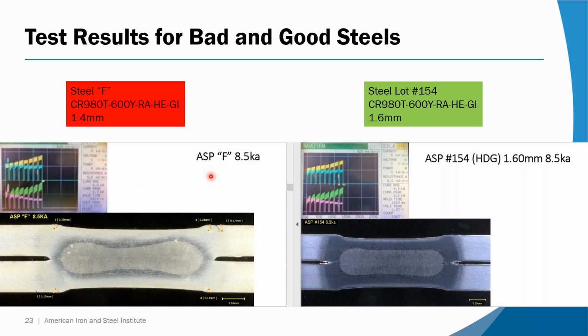8.5 kiloamps. This guy made some little cracks at 8.0, and now they're getting deeper and more prevalent. This material on the right, still no cracks. Everything's calm and good. So roughly equal treatment is producing cracks in this material, but not in this material.